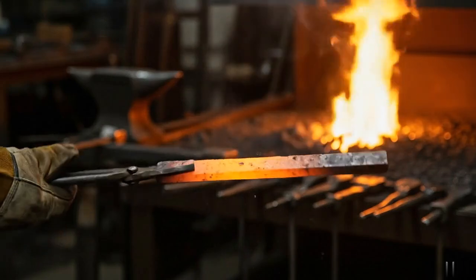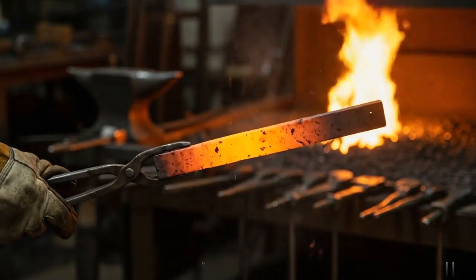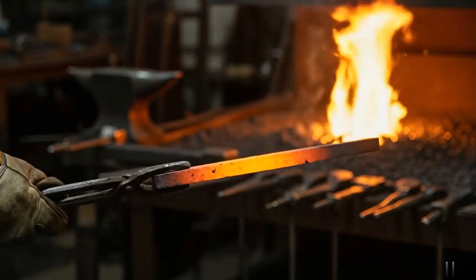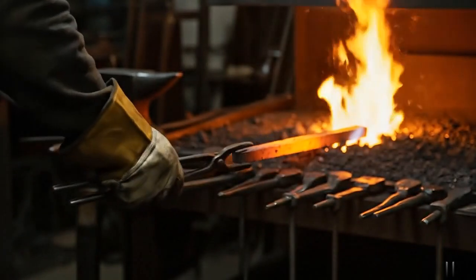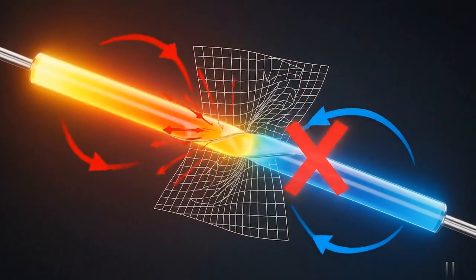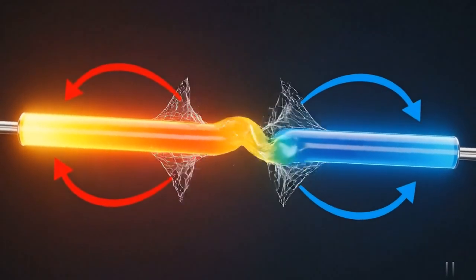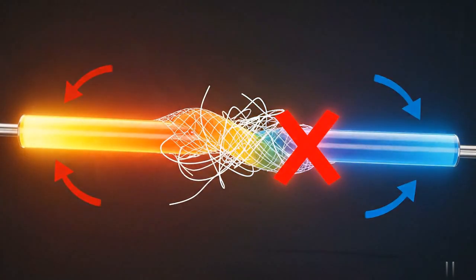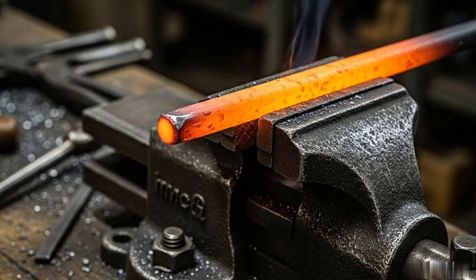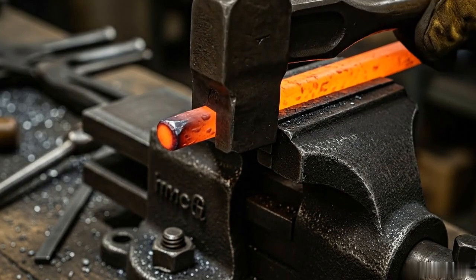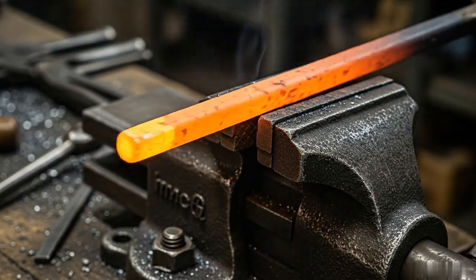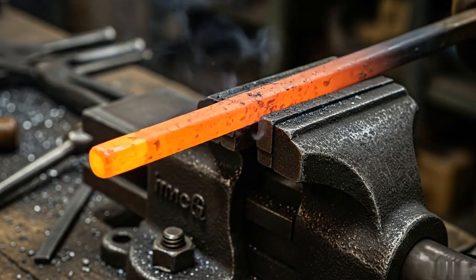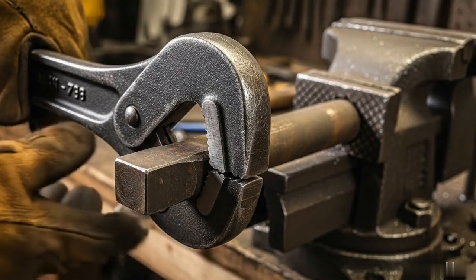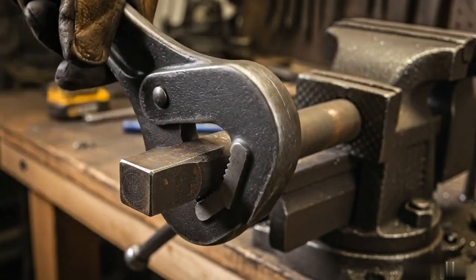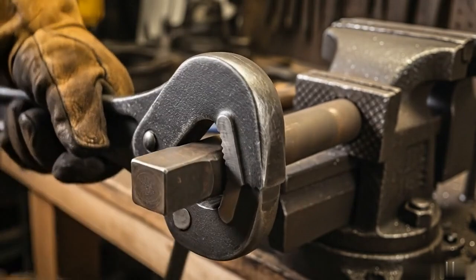Focus on the middle third, heating it to a perfectly uniform orange color for the twist. If one part is hotter than another, it will twist unevenly and ruin the symmetry of the pattern. Once the heat is right, I lock the tip of the blank into a heavy vise quickly. I clamp a big wrench onto the tang, and with slow, controlled force, I twist the bar.